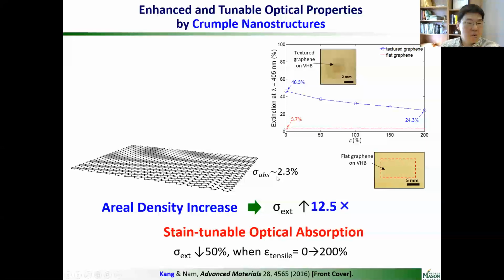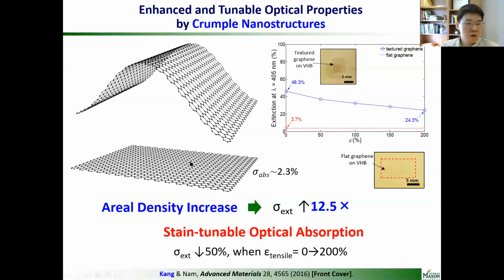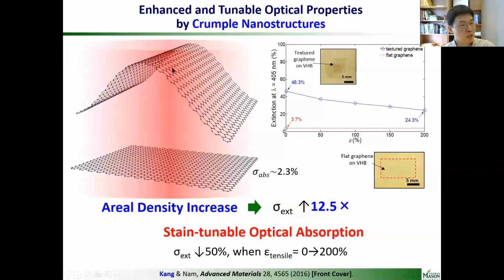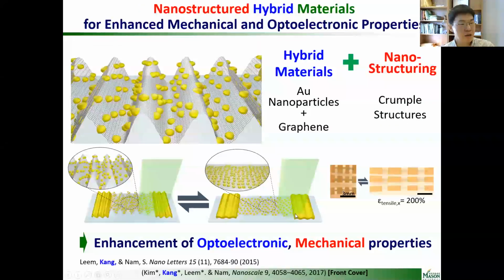So how could we use these structures and materials? The mechanism is that we can increase the areal density. Compared to flat graphene, as we create these wrinkles, you can imagine that as we absorb the light on the structured graphene, we increase the area for absorbing the light. That way we can increase the absorption of light, so that we can increase the sensitivity to light.